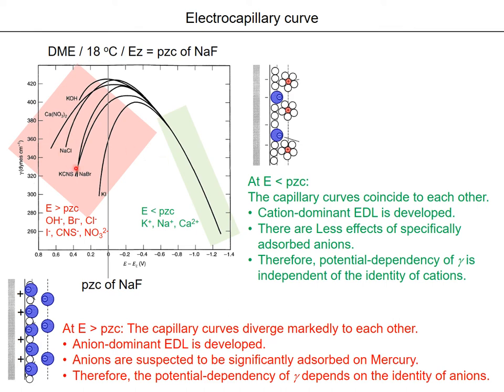Let's go to the other side. At potentials more positive than the point of zero charge, the capillary curves diverge markedly from each other like that. KI here, sodium bromide there, KOH here, calcium nitrate there, something like that. In this situation, for the positive potential, an anion dominant electric double layer is developed like that. On the outer Helmholtz plane, of course, you should find the anions.